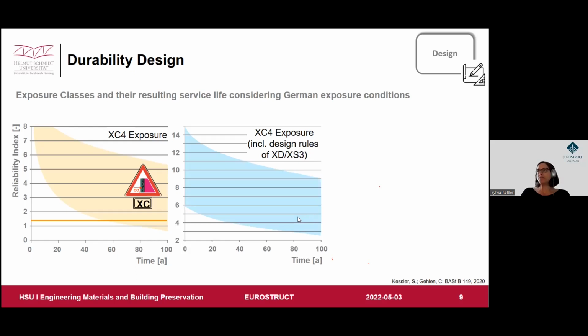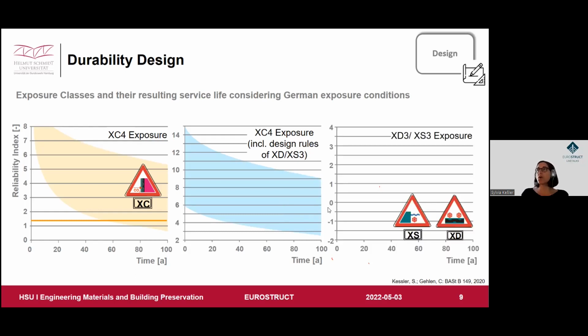But at the end, the most important thing is what is going to happen with the XD3 or XS3 exposure. Under this exposure class, we normally have cyclic wetting and drying in combination with exposure to chloride ions. And this is the most severe environment you can have when you are concerned about reinforcement corrosion. And you see that the scale of the reliability index has already changed.